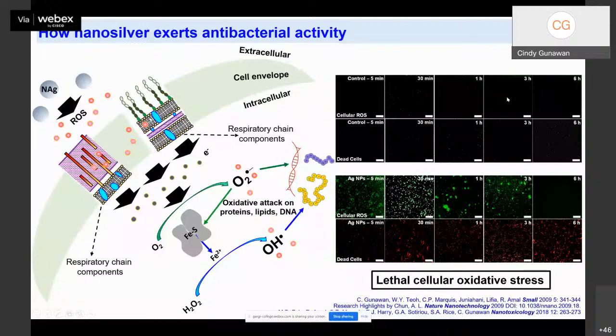On the top panel here, these are fluorescent microscopic images of the cell-only control, so no silver, and we dye the bacterial control with a fluorescent dye that can detect the cellular presence of reactive oxygen species, which will give us green fluorescence. And as you can see here with the control, we could only detect very low levels of reactive oxygen species, which are most likely byproducts from aerobic respiration.